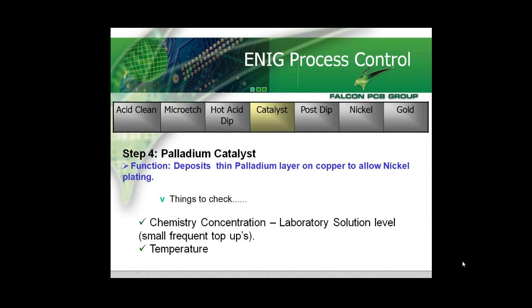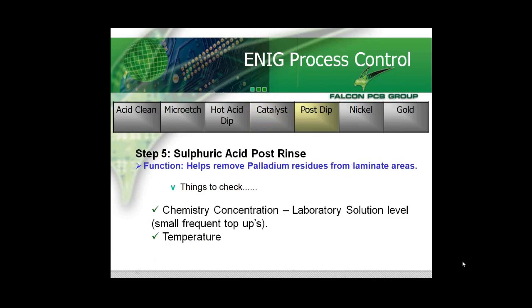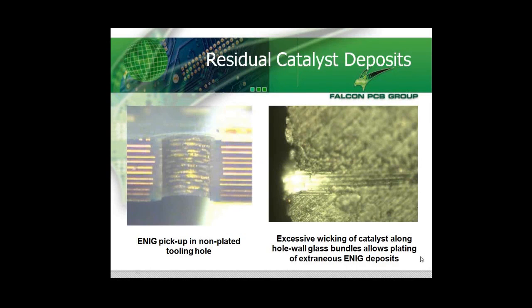Our next one is a palladium catalyst. Again, well described by Nigel. Fairly easy, not a problem process. The only issue that we have with this one is probably removing the catalyst from the areas that we don't want it on. And the sulfuric acid post-rinse, again, slightly differently described in the Atotech chemistry, but does exactly the same job. What we're looking to do is to eliminate the problem of a palladium catalyst actually wicking.